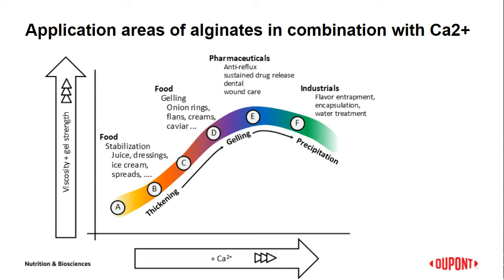If the calcium concentration is above a certain limit, the multi-layer junction zones precipitate the polymer from solution, which is used, for example, for water treatment or encapsulation processes. Please also note that if high amounts of calcium are already present in the water where the alginate should be hydrated, the polymer will not be dissolved in such a medium. The calcium source must be added when the alginate is already dissolved in most cases.